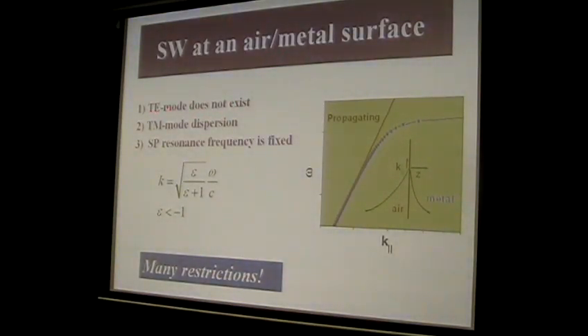First, the transverse electric mode does not exist. Second, it only supports the TM mode dispersion, and also the resonance frequency is fixed by the natural frequency. So this is the typical TM mode dispersion of the surface plasmon, and you will find that it has many restrictions. This plasmon resonance frequency cannot be changed. It can only be fixed by the material itself.